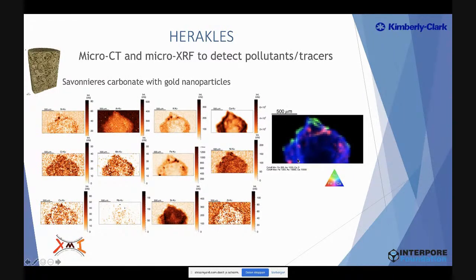But what you can also see is that you are missing all the internal information, and that is because XRF typically gives information about the surface and subsurface. As you can see here, most of the information is around 200 micron below the surface, more or less. This also depends on which element you're looking at. But so there is also a limit. It's more for superficial detection.